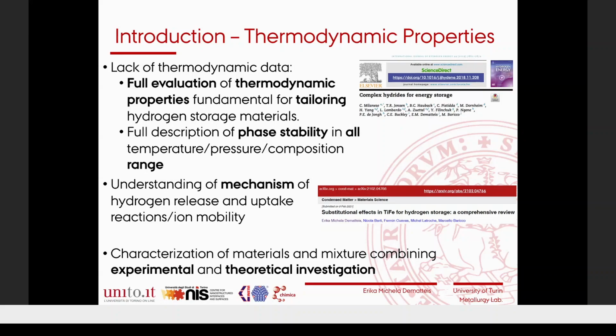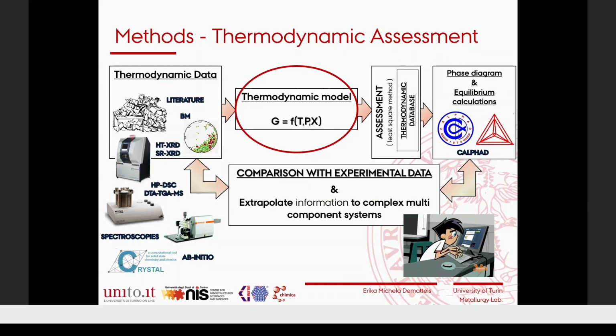So we collected some recent research in these two reviews that I propose in the slide. And I will show you today some results regarding the characterization of these materials, both from the experimental and the theoretical point of view. Our approach is to perform a thermodynamic assessment that includes the collection of thermodynamic data, both from the literature, but also by synthesizing new materials and investigating them by calorimetry, X-ray diffraction and spectroscopy, and also combining ab initio calculations.